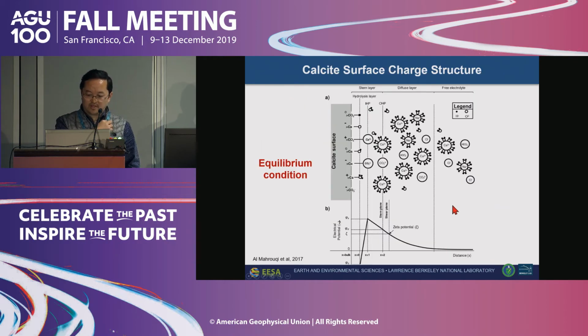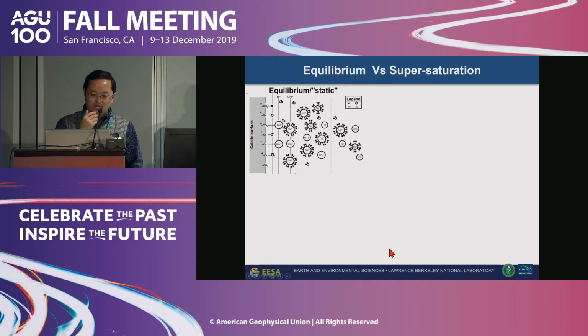So if we go back to the calcite surface charge structure, we look at the electrical double layer with the Stern layer, diffuse layer, and the free electrolyte, and what the potential profile looks like. And what we think is happening is that under equilibrium conditions, the electrical double layer is more or less in a static condition.